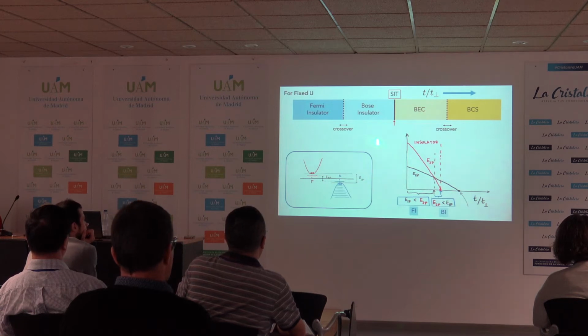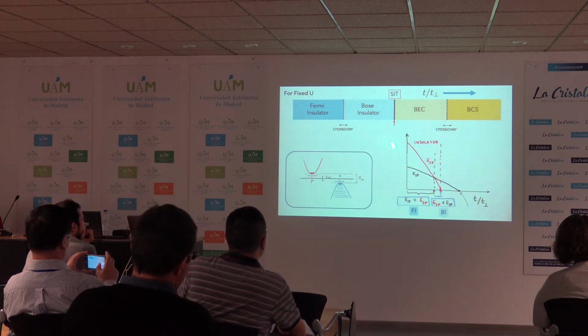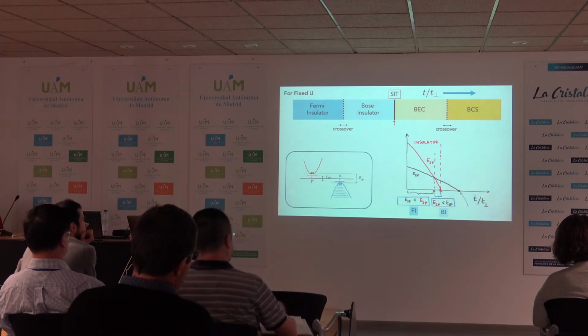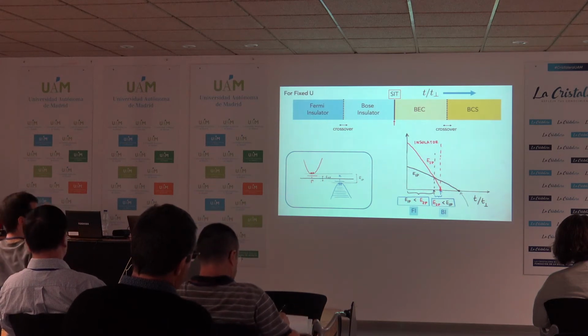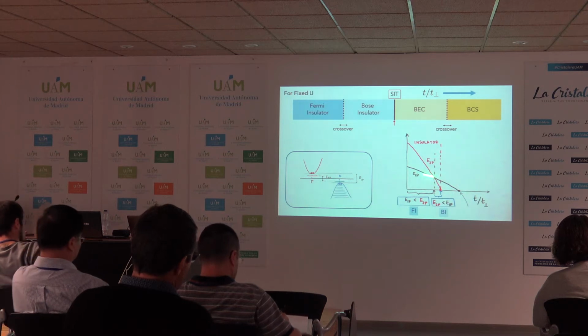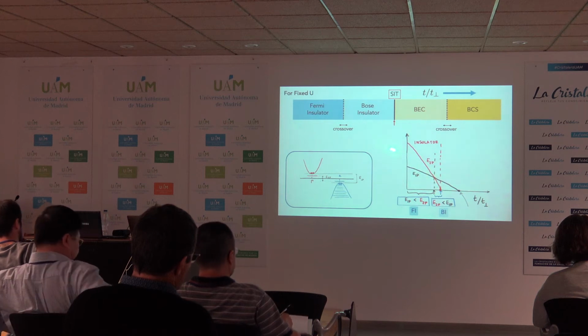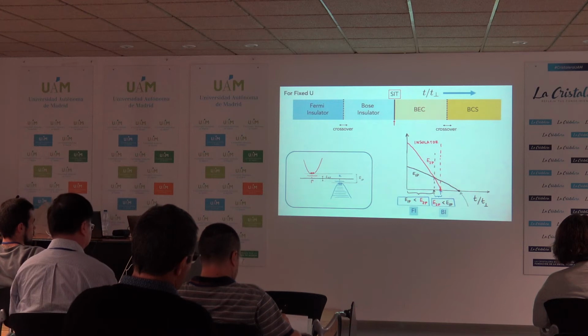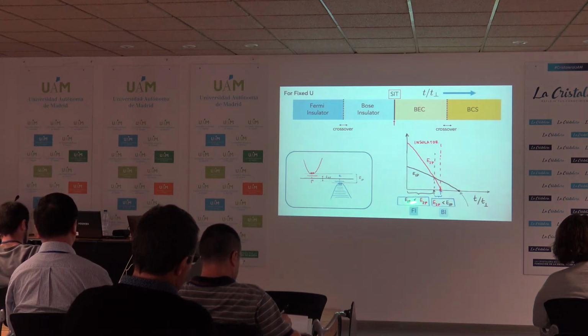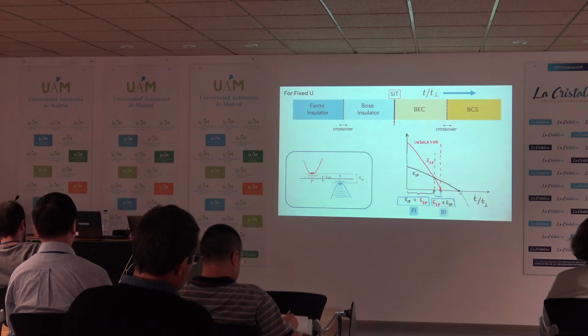So what you're seeing is at zero hopping, the energy to create two particles would have been twice the energy to create a single particle, right? Because you have to take two holes and put them into the conduction band. But if there is some attraction, the two-particle gap can start to become lower at some value of the hopping and dip down below the one-particle gap. When that happens, the system makes a transition from a Fermi insulator, where the single particle gap is lower than the two-particle gap, to a bosonic insulator, where it becomes cheaper to make a two-particle excitation compared to a one-particle excitation. So this is the precursor to the superconductor.